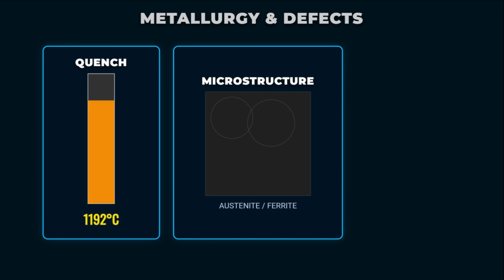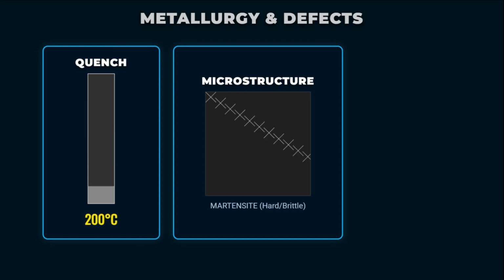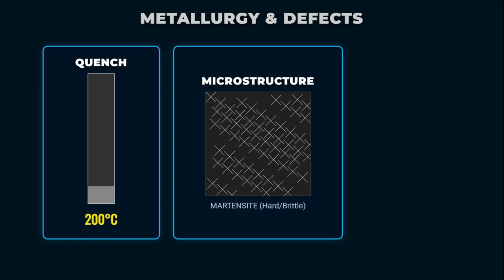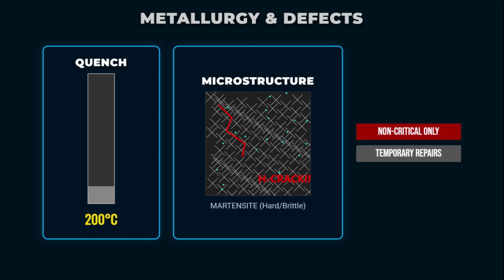The primary metallurgical challenge in underwater welding is the rapid cooling rate, or quenching, caused by the surrounding water mass. This rapid quench prevents the slow, controlled cooling necessary for optimal grain structure. In wet welding, the weld metal cools so quickly that it often forms martensite, a hard and brittle microstructure with low ductility. Furthermore, the high hydrogen content trapped in the weld metal leads directly to hydrogen-induced cracking, also known as hydrogen embrittlement. This severely limits the application of wet welds to non-critical structures or temporary repairs where high fatigue resistance is not required.